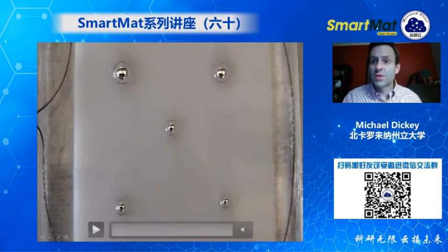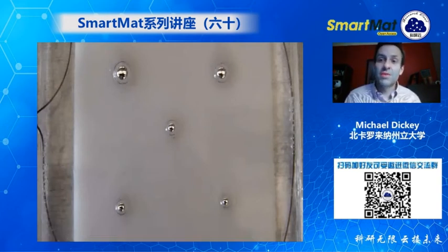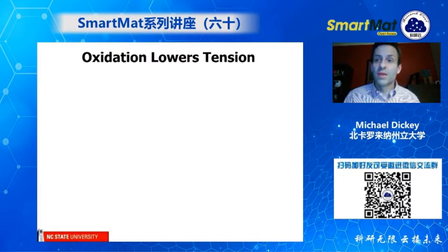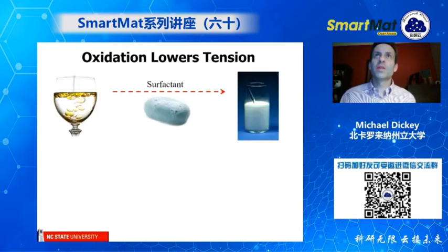And so this is kind of a long story, and I don't have enough time to tell everything, but I want to just tell you the main points. The main point is that this oxidation really lowers the surface tension. So if you wanted to lower the surface tension between, let's say, water and oil, you would do it by adding soap. We call this a surfactant. The soap goes to the interface between the oil and the water, and it can form something that looks like milk.